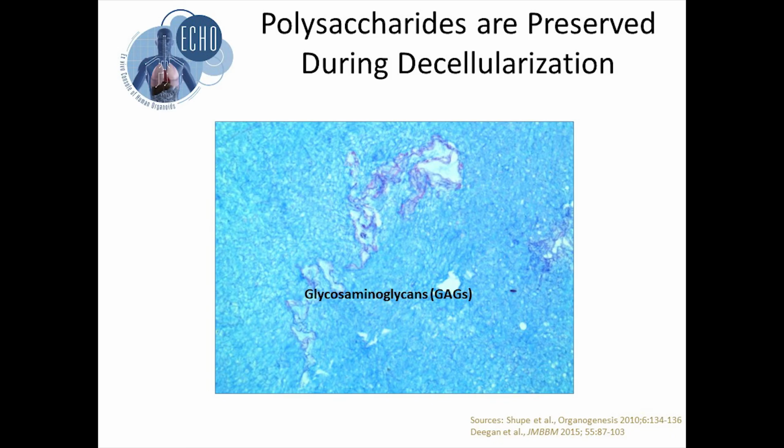The reason we want these in the hydrogels is because we want growth factors that are either added to the system, or autocrine or paracrine factors that are produced within and around the organoids, concentrated near the cell surface where they can associate with the receptors. Having these glycosaminoglycans that are able to bind signaling molecules and bioregulatory molecules holds those components near the cell surface where they can act.